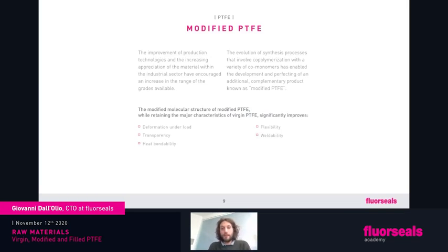And this is really helpful when we raise the pressure in our application, because we don't want the pressure to modify the shape of our seals or any kind of application. Modified PTFE is also more transparent. It is heat bondable and weldable, and that's quite useful in certain applications where we have to weld different parts made of PTFE. PTFE doesn't like to be welded. Modified PTFE is quite easily weldable.